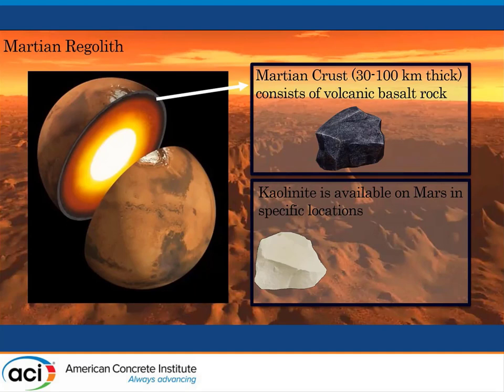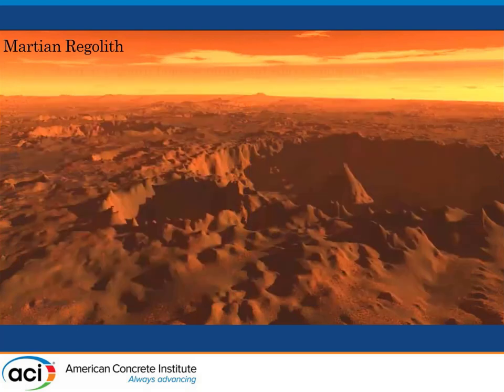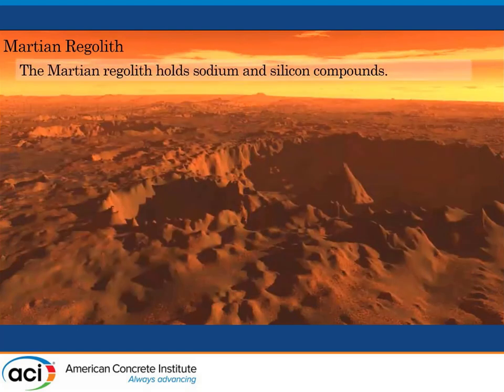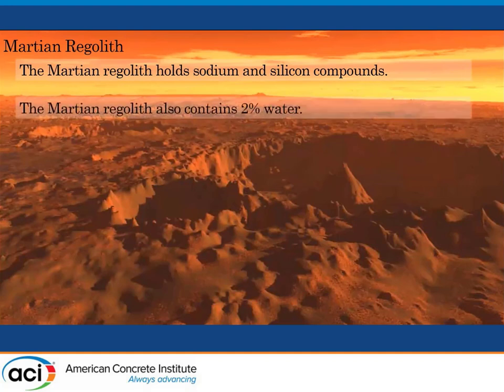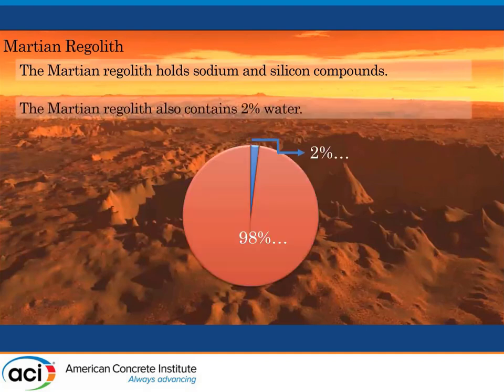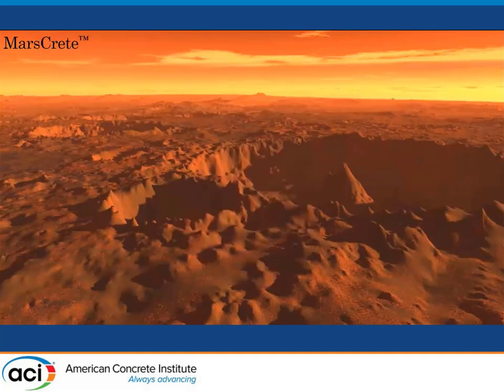Kaolinite is a layered silicate clay mineral that could be calcined to form metakaolin. Metakaolin could be another source for making concrete on Mars. The Martian regolith holds sodium and silicon compounds as well. And also the Martian study indicates that the Martian regolith also contains 2% water in frozen state. So we assume that we are able to use this water for construction.